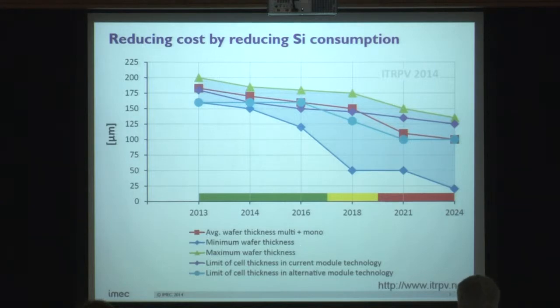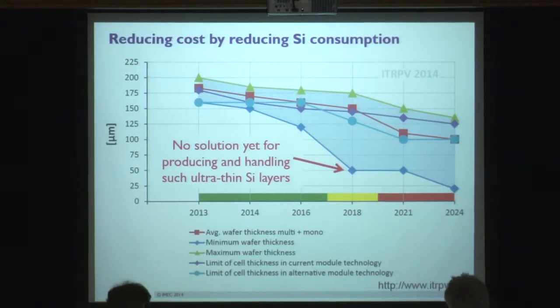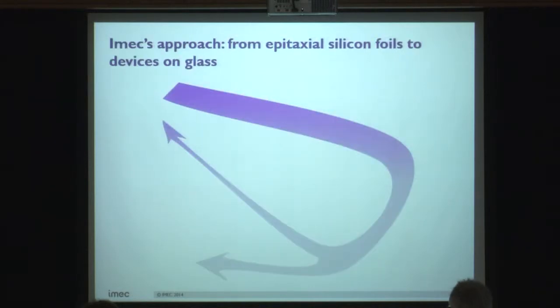But of course, to be able to do that, there are some problems that need to be tackled. First of all, how can you make a 50 micrometer or even thinner crystalline silicon layer? And secondly, if you have such a very thin layer, it becomes flexible, but it's also very fragile. So you need to have new ways of handling such a very thin material and processing it into a device. So now in the next slide, I will show you the approach that we are developing at IMEC to tackle these issues. And this is based on the use of porous silicon and epitaxy.